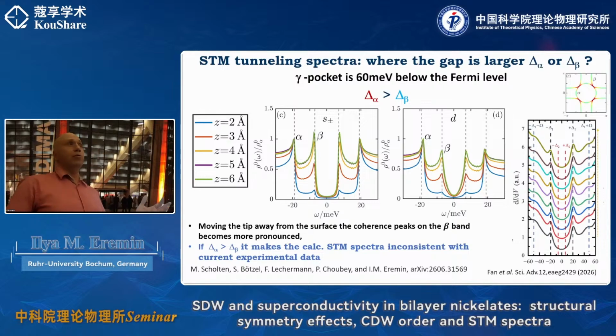It tells you that in the STM, it will be hard to say whether the symmetry is s wave or d wave. However, it can also be considered good news, because in principle you can now try to change the position of the tip with respect to the surface. And by doing this, you will be able to visualize whether the nodes are indeed there or not.